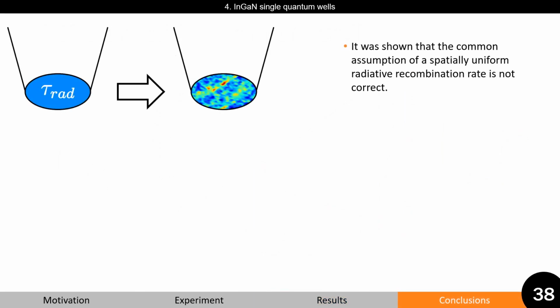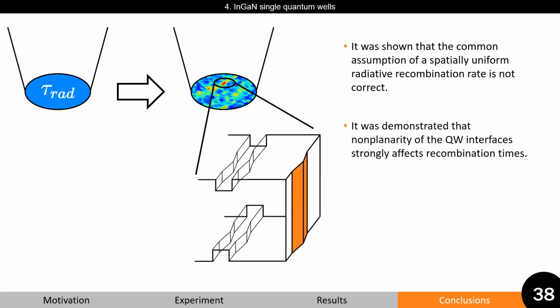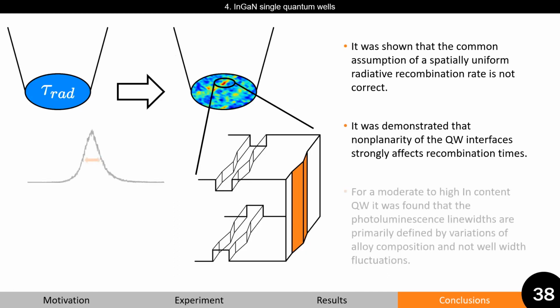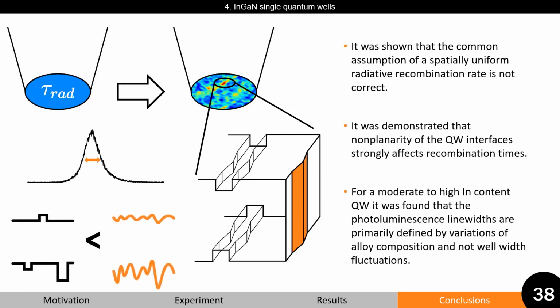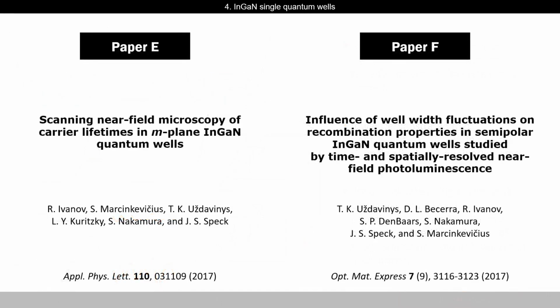In the last set of conclusions, it was shown that the common assumption of spatially uniform radiative lifetimes is not correct. In addition, the non-planarity of the quantum well interface can strongly affect radiative lifetimes. And finally, for moderate to high indium content quantum wells, photoluminescence broadening is primarily defined by composition variations. Results were published in papers E and F.